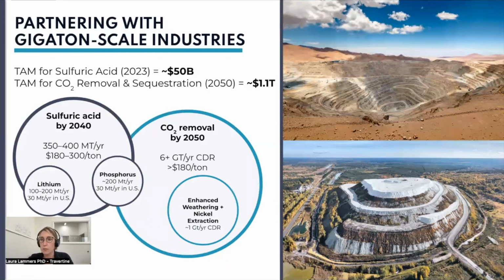So why this approach? The rationale for getting into the extractive industries is that these industries are operating at the hundreds of millions of tons, a billion ton per year, orders of magnitude similar to the cement industry, producing waste at those scales. And so we have feedstocks for carbonate mineralization that are of the order of magnitude required to eliminate emissions for cement production, for example. And so sulfuric acid, which is the extracted chemical that we produce, today is producing quantities of up to 300 megatons per year, 300 million tons per year. And that's projected to grow significantly to 350 to 400 million tons per year by mid-century. And of course, the need for carbon removal and durable sequestration is growing exponentially as well.